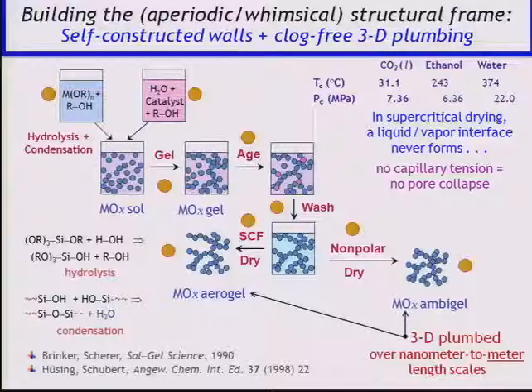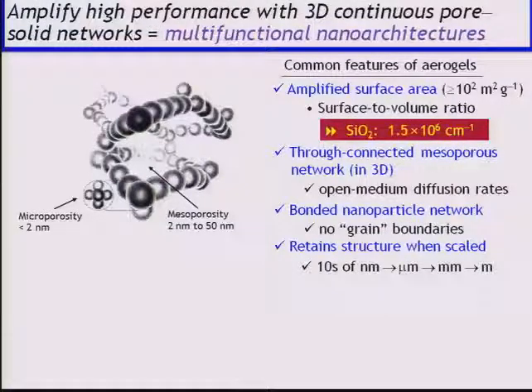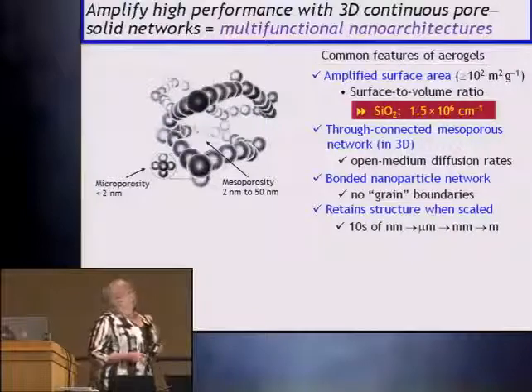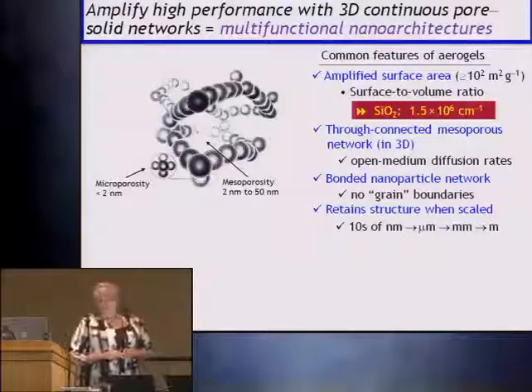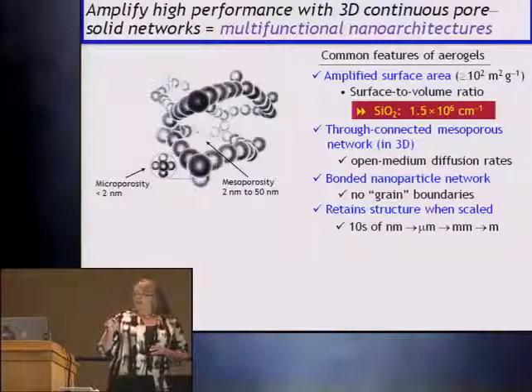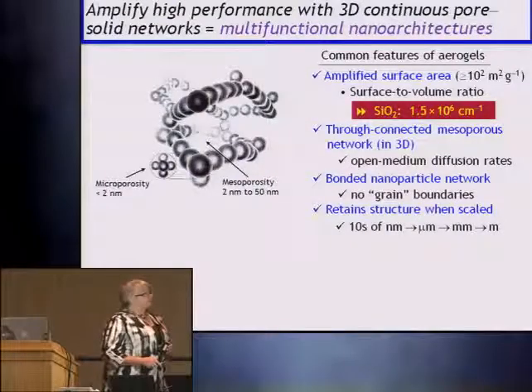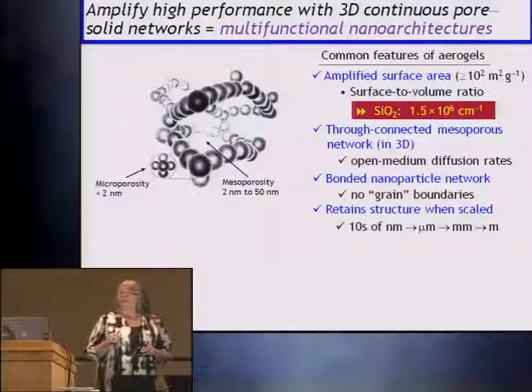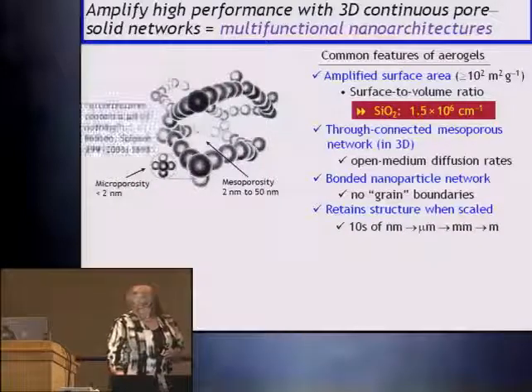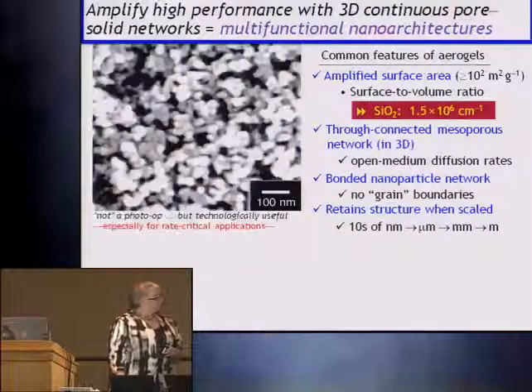And anywhere you see the bouncing gold ball, a chemist can come in and change the function. So to summarize some of the things that a structure like this walks in the door with is as much surface area as you can get based on the molecular weight of your oxide. So for silica, you're over 1 million per centimeter in your surface to volume ratio. That's amplifying what you care about if you're a surface scientist, the nature of that surface. The plumbing is stayed 3D, so you get very close to open medium diffusion rates. The particles are bonded. So if you're moving charge, that's important. That does not introduce junctions or impedances.